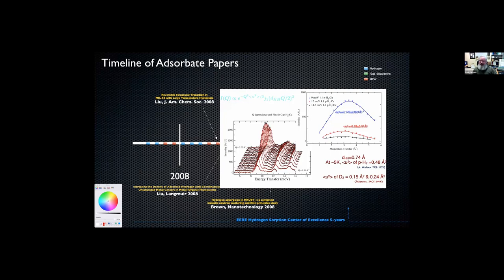We could also get the Q dependence of those transitions using a cold time of flight triple axis. Here we're showing the integrated intensities of those individual peaks that are related to the different manifold transitions. What we learned from this is that you can describe the Debye-Waller factor, essentially how free the hydrogen molecule is compared to bulk hydrogen, and it's really tightly bound. It's limited in terms of the space volume that it can feel while it's attached to that metal center.